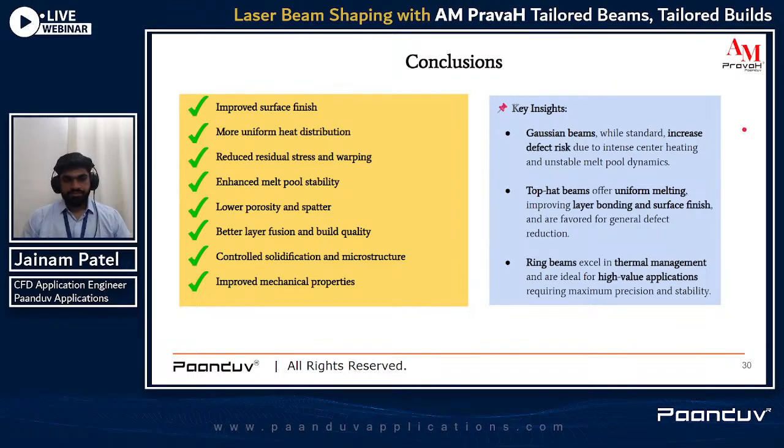So, conclusion. We have found that it will improve the surface finish, give more uniform heat distribution, reduce residual stress and warping, enhance the melt pool stability, lower porosity and spattering, give better layer fusion and build quality, control solidification and microstructure, and improve the mechanical properties.